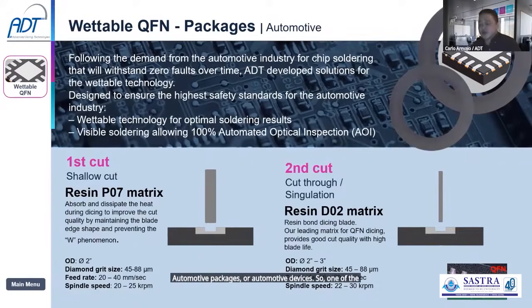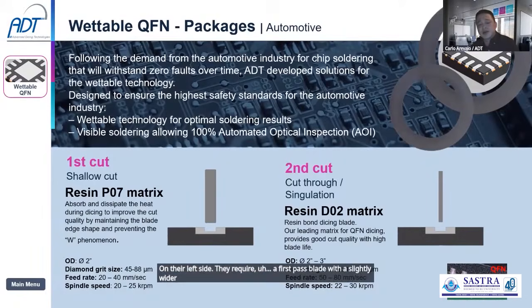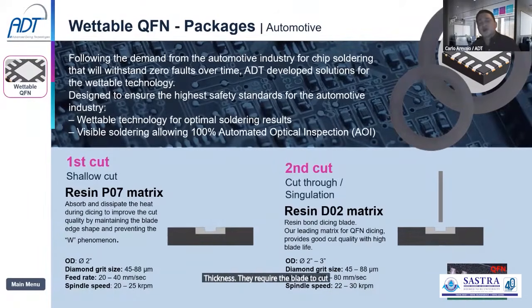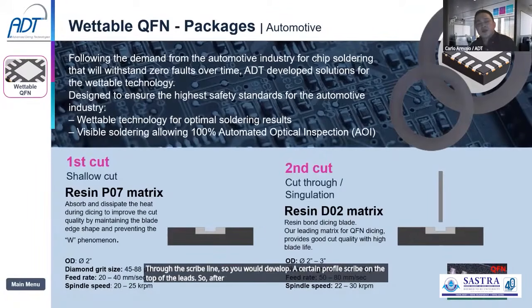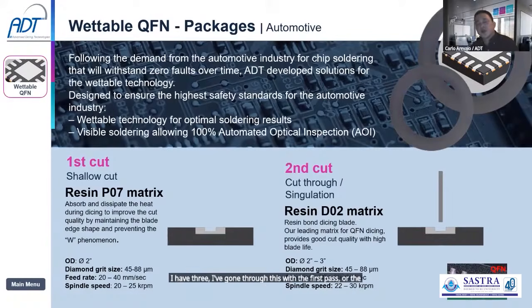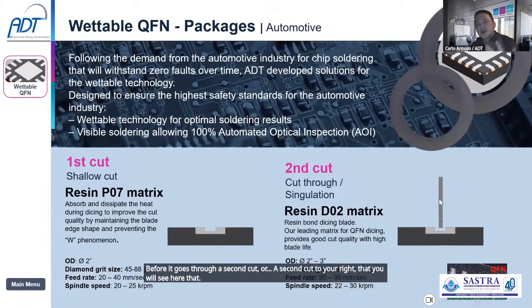So one of the things that was changed here from the normal QFN process flow was to improve the plating process. Here on the left side, they require a first pass blade with a slightly wider thickness. They require the blade to shallow cut through the scribe line, so you develop a certain profile scribe on the top of the leads. After you have gone through the first pass, the shallow cut pass, the lead frames will go again for another plating procedure before they go through a second cut, to your right, that you will see here, that will full cut the unit.